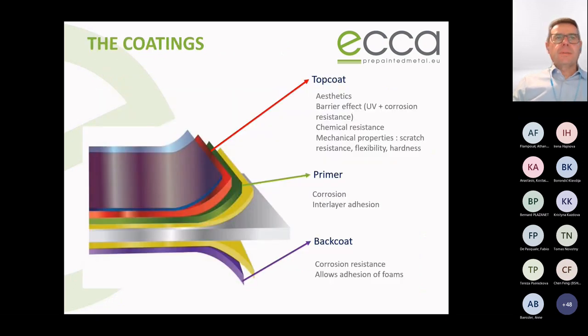Coatings have to provide protection against different factors, like, for example, moisture, UV rays, atmospheric pollutants, microbial growth, corrosion, or surface cracks. In coating of pre-coated metals, we use a multi-layer paint system to achieve those goals. Top coats are responsible for aesthetics, barrier effect, chemical resistance, and mechanical properties like scratch resistance, flexibility, hardness. They are applied over primers, whose function is to deliver corrosion protection and ensure interlayer adhesion.